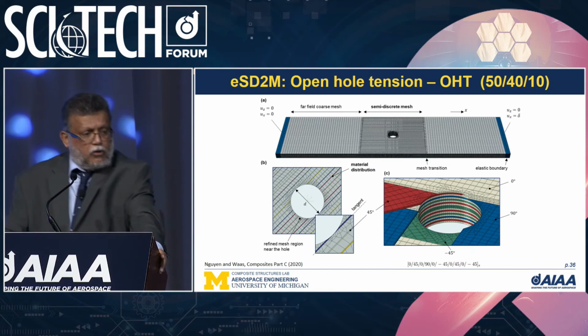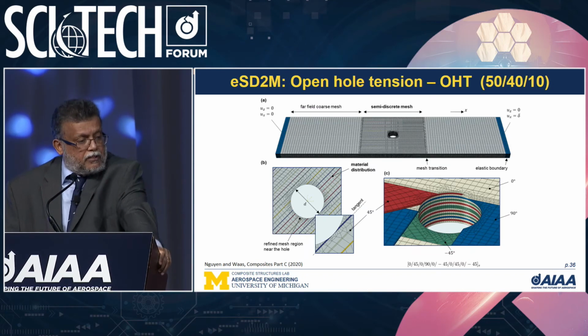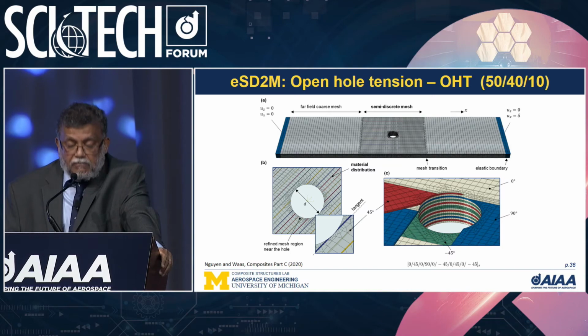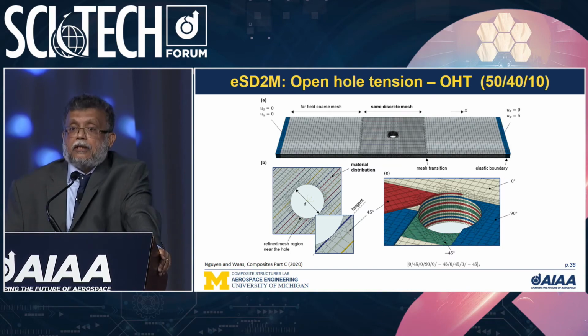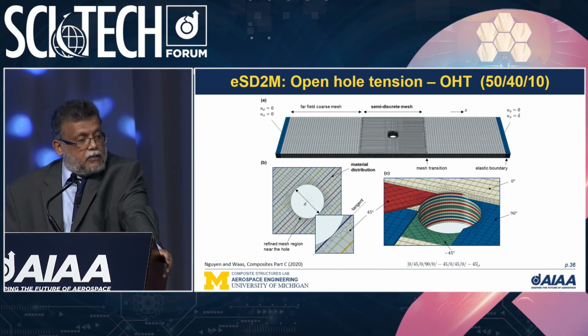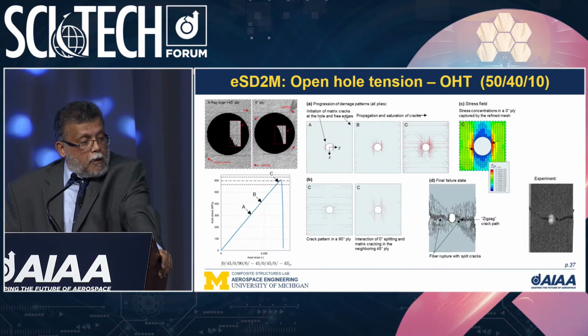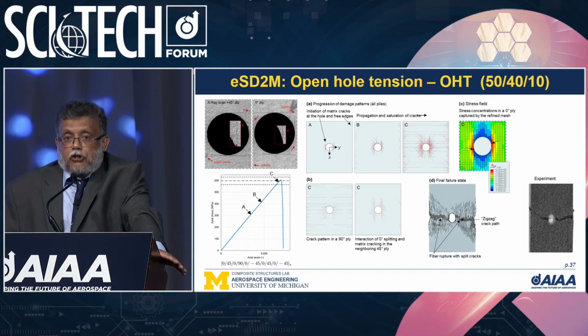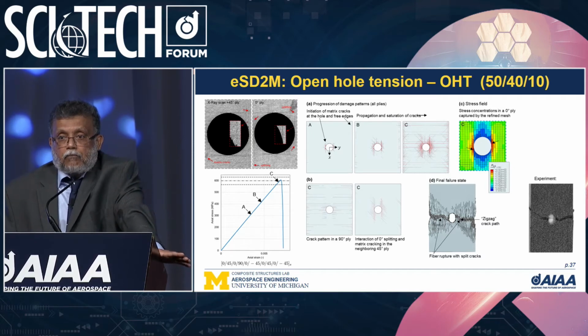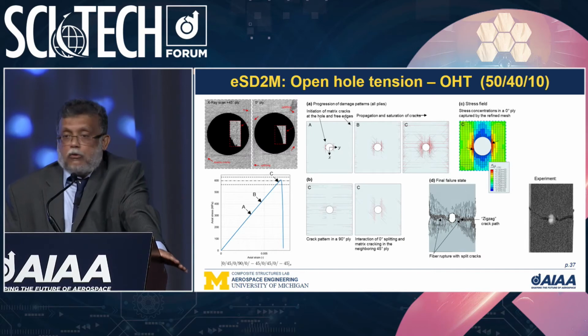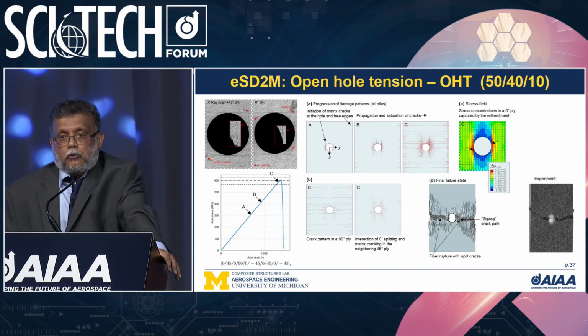Here is an open hole tension challenge that was presented to us by the Boeing company, showing the smart meshing tool, and I'm going to show predictions for this particular laminate. What's interesting is to see how edge cracking, splitting at the hole, is captured very early on. The splits occur almost at 50% of the ultimate load.